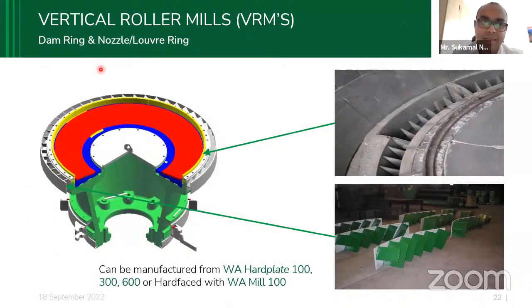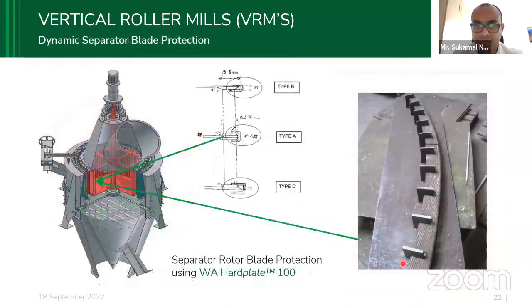Here is exactly the same thing, called a dam ring and nozzle. It can be manufactured with a hard plate. What a hard plate is, is a special type of plate where we put a hard facing layer of complex carbides, which enhances the life of these rings. The same thing is shown here, where this kind of part fits in the rotor blade.